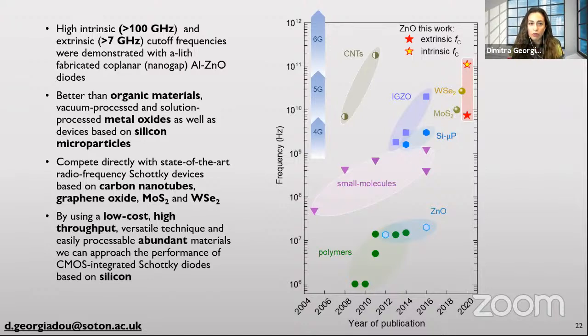Then another thing I have not mentioned here is that some of the devices are encapsulated and some of them are operated in air. So until we find the proper way to encapsulate, of course, we will continue seeing this huge difference between the intrinsic and the extrinsic cutoff frequency in our devices. There are several things to consider here. For example, if we encapsulate, we add capacitance on top of that. We have seen the effect of that also in intrinsic cutoff frequencies. But all these parasitic capacitances contribute hugely in the measurement of the extrinsic cutoff frequency.